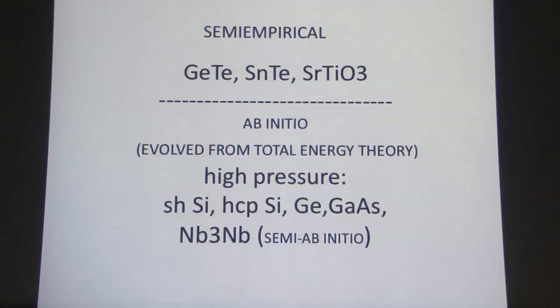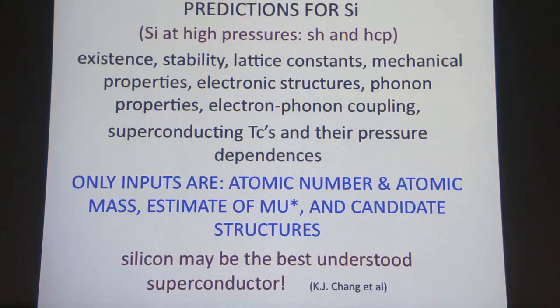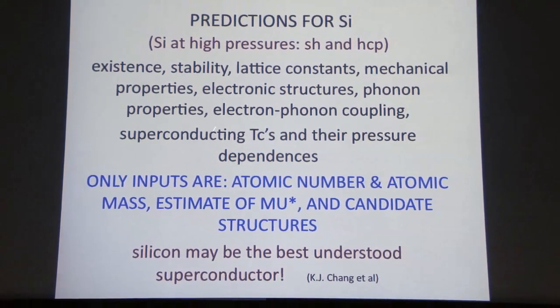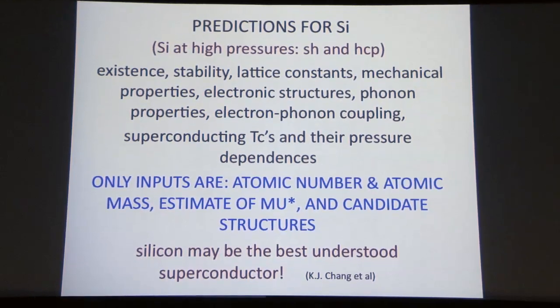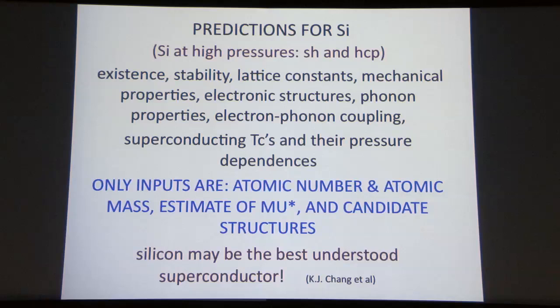So let me quickly tell you that in the early days, we could predict that some materials would be superconducting using semi-empirical approaches. But now, in fact, we can start along the lines of the beginning of the lecture with this quantum alchemy. We could predict that silicon, even under high pressure, will become a metal. We can predict its structure. We can predict everything about it, its existence, its stability, its lattice constants, and even its superconductivity. And the only thing you have to put in is the atomic number and the atomic mass of silicon. And so these new silicon materials, which didn't exist before they were predicted theoretically, were found, and they're superconducting. But they're not really very high temperatures.